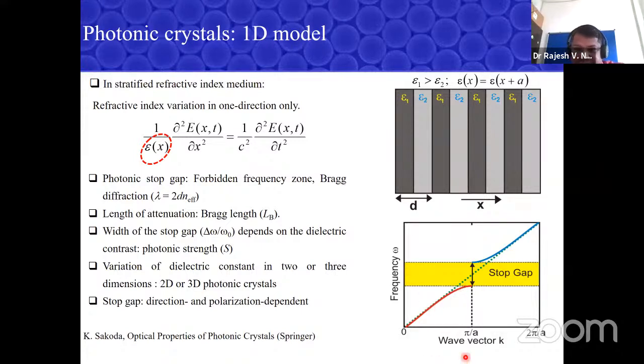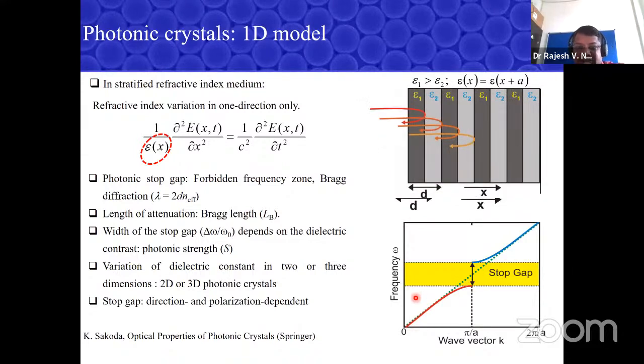The frequency versus wave vector shows a break in the dispersion relation. If you look at this yellow region, at some frequency range there are no propagation constants, and the dispersion relation shows a discontinuity. So what happens at these frequencies? Suppose I launch light into the structure at a frequency within this yellow region: the light gets Bragg diffracted back. The light cannot propagate. That means there is no allowed wave vector in the system where the light can couple. In fact, all the light returns back and interferes constructively according to the Bragg condition.